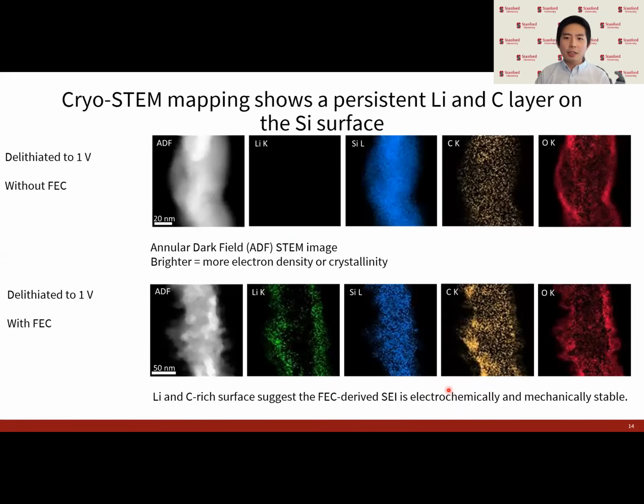And for comparison, these are the two electrolyte systems. Up here is without FEC, down here is with FEC. And we can clearly see that there are significant differences in the SEI behavior on delithiation on the silicon surface, and that the SEI with the FEC additive is much more stable than without.